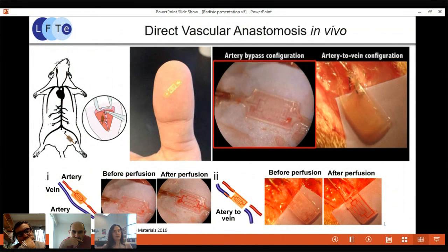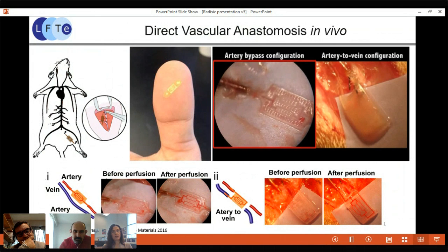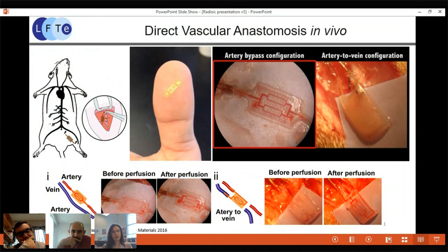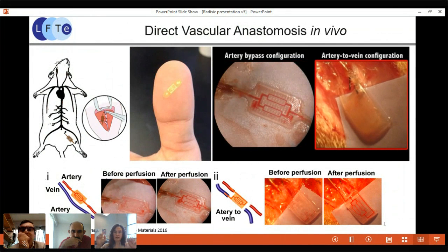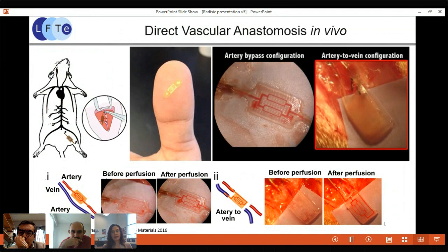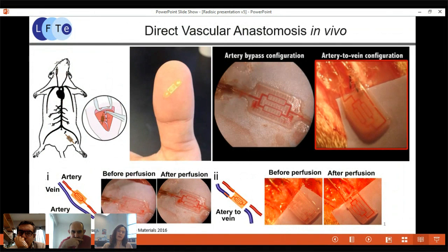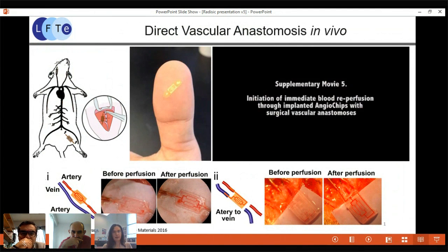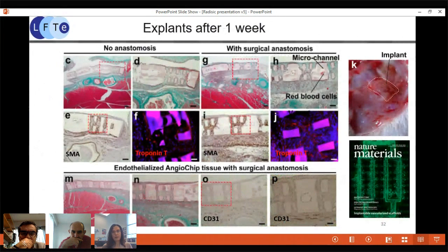So this was really one of the first, probably the first polymeric system that doesn't include the use of autologous vasculature, such as that in flap surgery, that enables you to hook in the plumbing, hook in the vasculature directly and establish the flow directly in the scaffold and immediately upon implantation. And you can see that we have artery bypass configuration and artery to vein configuration that we can use the scaffold in both settings. The tissue in this particular case remained implanted for 1 week, and you can see very nice tissue integration at the time of explantation.